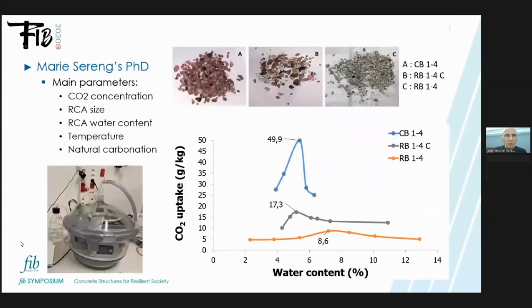We have a PhD that will be finished this year, and Marie has studied a lot of parameters: CO2 concentration, the size of the aggregate, the water content, temperature, the natural carbonation. And here you see the effect of water content, it's like in natural carbonation, there is an optimum for the water content. And also here you see the effect of natural carbonation.